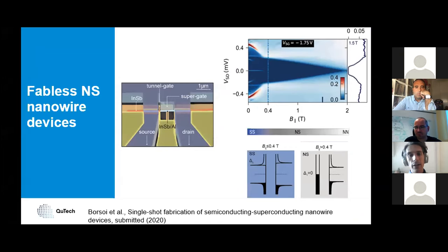If you look at the data at zero Tesla, we are looking at an asymmetric Josephson junction. In this kind of device, you have a multiple Andreev reflection pattern, which derives from both gaps. So we have the delta one plus delta two peak at, let's say, 0.5 millivolt. But we can also distinguish both gaps. One is typically 250 microelectron volt, and the other one is typically 200. So this already gives you an idea of how the thickness changes the gap.